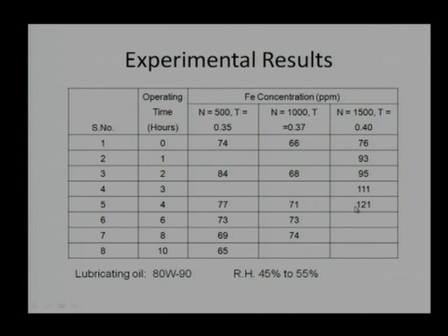This means more and more corrosion happens to the surface, even though we know the gear lubrication mechanism, or that this lubricant additive is known to be one of the very good gear lubricants, and still we are getting this kind of wear particles. That means the gears will never work in the hydrodynamic domain, it will never work in a fluid film lubrication mechanism. Now, working in a mixed lubrication or boundary lubrication, that is why we are getting wear particles, and the particle percentage is increasing with increasing speed.